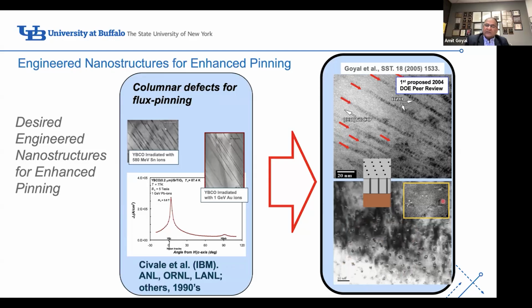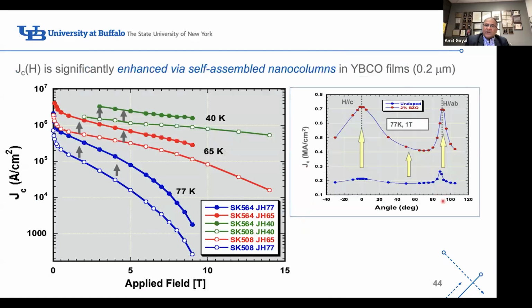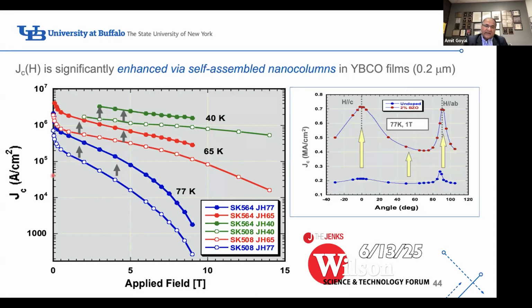When you have these nanocolumns, and when you don't have these nanocolumns, at 3 different operating temperatures of 77, 65, and 40 Kelvin, you can see the amount of current you can carry increases dramatically. This is an exponential axis here. And of course, you can change the field orientation, which is important for rotating machinery applications. But in the entire angular range, we can increase the performance of the superconductor.